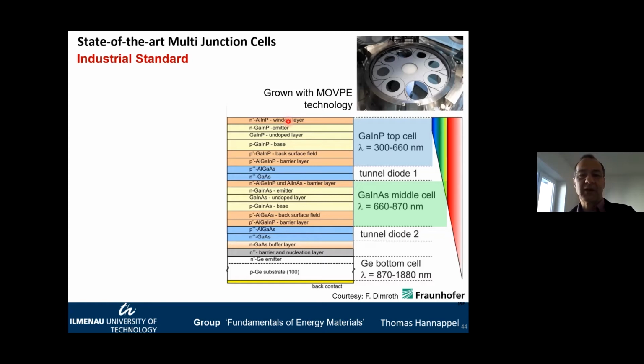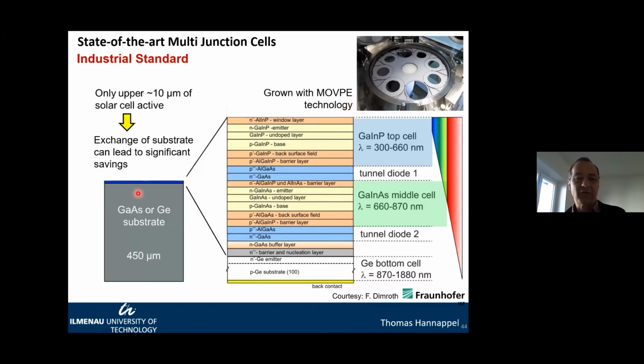This is a typical high efficiency III-V solar cell, which is normally grown by the so-called MOVPE technology. MOVPE is metal organic vapor phase epitaxy. It's also called metal organic chemical vapor deposition, MOCVD. And one of the important points here is, of course, that we use a very expensive substrate. This very expensive substrate normally is made of a III-V material like gallium arsenide or germanium.